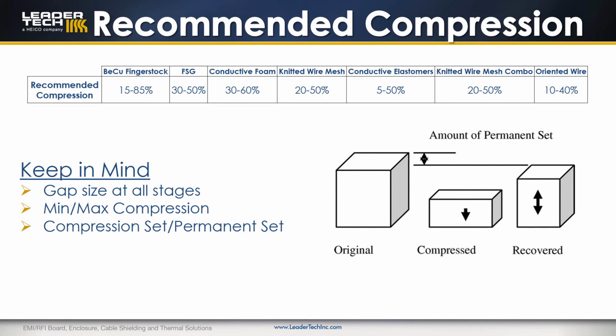Over-compressing the material can also cause issues. The material can break, and over-compressing conductive elastomers can create separation between the metal particles and reduce conductivity. Compression set and permanent set is also possible, and for some materials may occur within the recommended compression range. Depending on the size, temperature, percentage of compression, and the amount of time compressed, the material may not rebound fully to its original height. This is compression set. For some applications, such as low cycle or permanently closed gaps, the compression set may not affect the application.